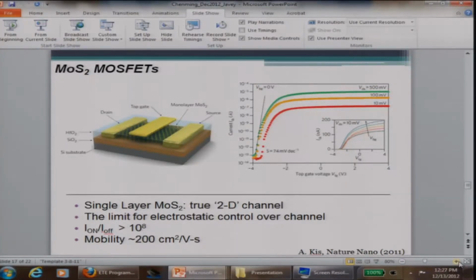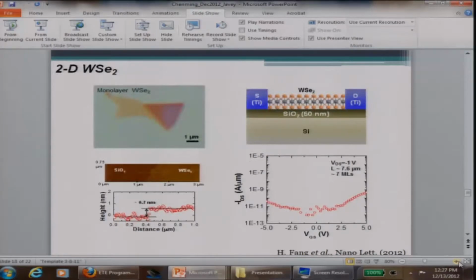And they were able to show that you can get a very high Ion/Ioff, and you can get pretty good mobility. The mobility in this case is for electrons. It's about 200 centimeters squared per volt second. You may not jump up and down at first, but remember, this is a single monolayer. The body thickness is 0.7 nanometer. For 0.7 nanometer, a mobility of 200 centimeters squared per volt second is quite impressive. So motivated by this, we started looking at other material systems that are also layered.